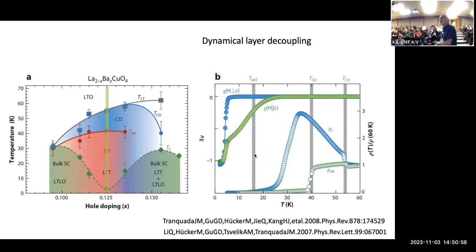So what's being shown here, in blue, is the resistance in the C direction, perpendicular to the copper oxygen planes, as a function of temperature. In green, the resistivity in the plane, the AB resistivity. This has been rescaled by a factor of 10 to the third. The high temperature anisotropy in the resistivity is a factor of 1,000. But what you can see is that as the stripe order develops, the anisotropy increases, but then something very dramatic happens. The system roughly looks like it goes superconducting in 2 directions while remaining highly resistive in the third.